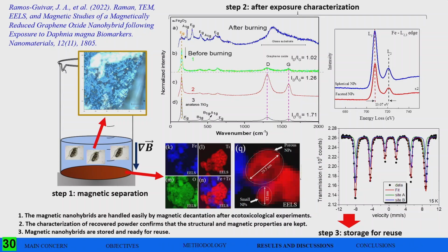Finally, I want to say that after the exoskeleton of the Daphnia magna is molted, we can recuperate the magnetic nanoparticles. We can, of course, clean them, wash them several times, and again make the Mössbauer spectrum to notice if there are any changes in the magnetic structure. And interestingly, we have seen no changes in the composition of this maghemite, nano-maghemite at 15 Kelvin.